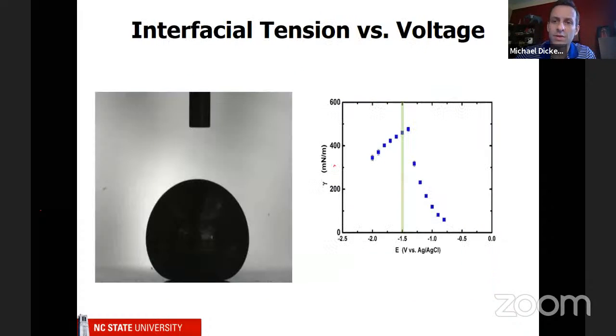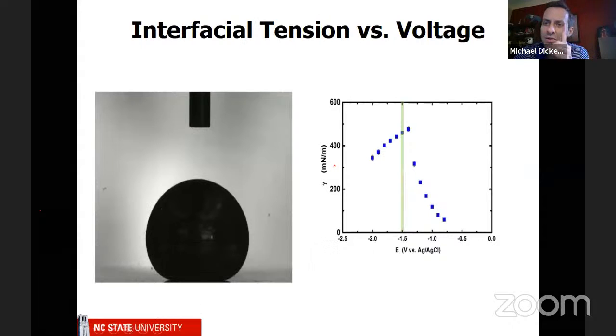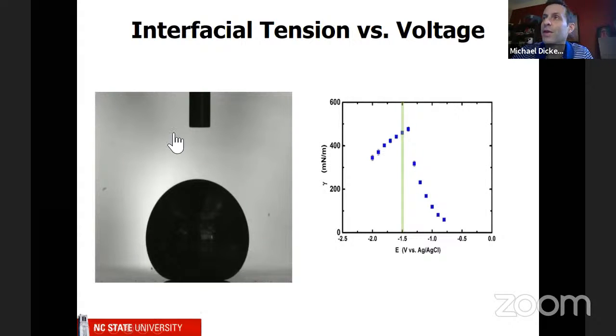All right, so here is our experiment. Again, you're looking at a droplet of the liquid metal. There's a little electrode that sticks up and touches it from the bottom. And there's a counter electrode, which you can't see. It's somewhere, I can't remember, somewhere over here. And what we're going to plot over here is the surface tension. So remember, water is 70. So water is right here. Gasoline is right here. So most fluids you encounter are way down here. And we're going to measure it as a function of voltage.